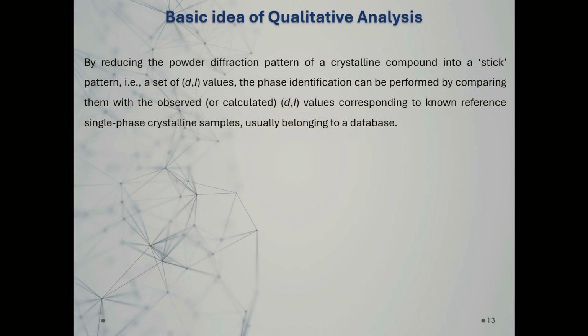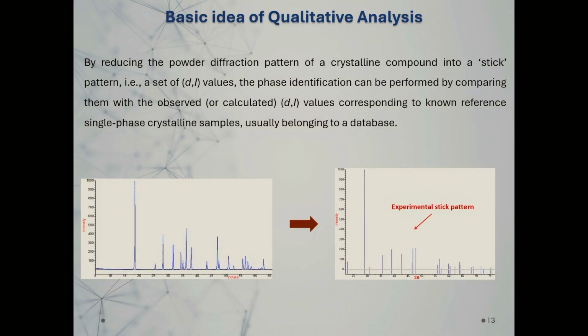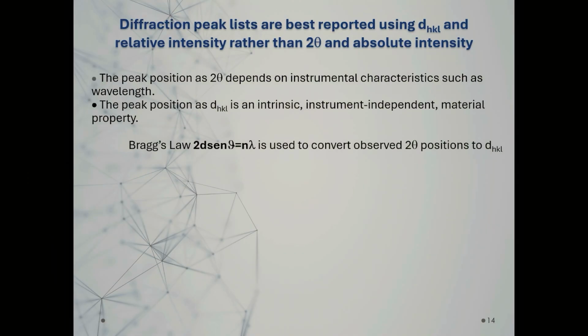So the basic idea of the qualitative phase analysis is to reduce our diffraction pattern into a stick pattern. So we have a set of d-hkl values, and the phase identification could be performed comparing the observed or calculated values corresponding to the known reference single-phase crystalline samples belonging to a database. So as here, we have a powder diffraction pattern that is reduced to an experimental stick pattern.